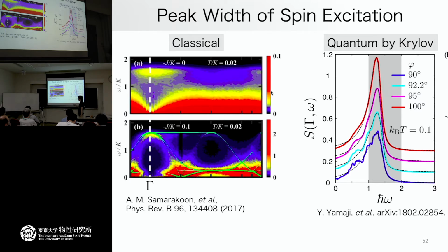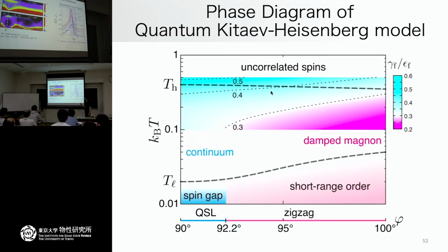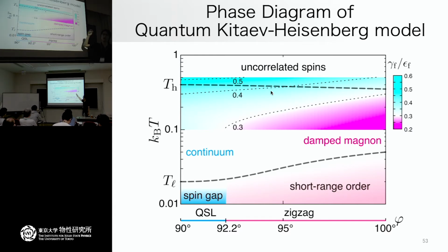Right. This is the reason why I mentioned some typical scale in the finite temperature spectrum in the experiment. It's like 0.1. So far, with neutron scattering, the resolution or finite temperature broadening, in the square lattice Heisenberg model is just around 0.1 in this width. So we can compare with this scale. Even at finite temperature, the experiment gives us some limit, 0.1 or something. If our curve goes below this scale or just points along this scale, then we can judge that you will have a well-characterized magnon dispersion, a damped magnon dispersion at finite temperature. This is the reason why I call this behavior a damped magnon.